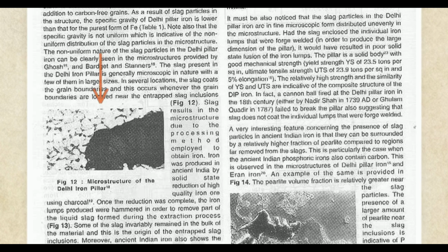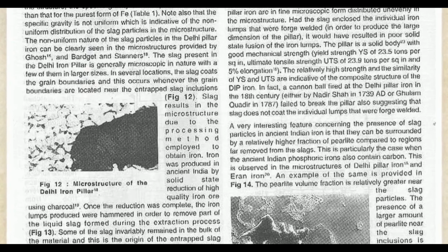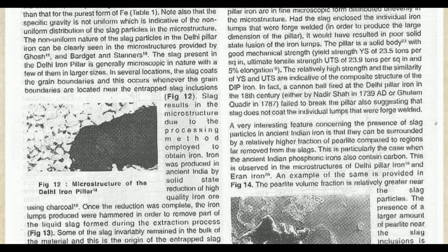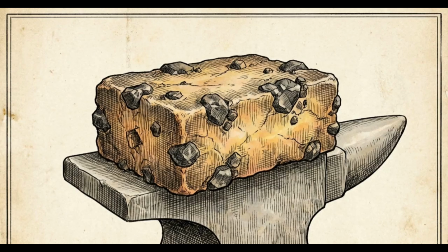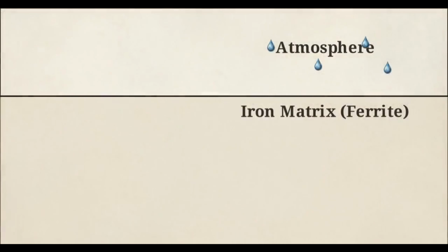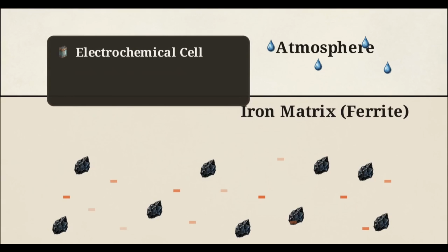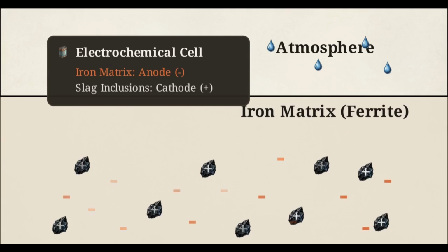Notice the large, dark, and trapped slag inclusions scattered among the ferrite grains. This solid solution contains high phosphorus iron interspersed with unreduced iron oxides and fayalitic slag. By omitting lime and vigorously hammering the metal, these iron makers produced a composite pregnant with the exact catalysts required for its future passivation. When exposed to the atmosphere, this composite structure triggers a specific electrochemical reaction. The iron matrix acts as an anode, while the entrapped slag particles operate as miniature cathodes.